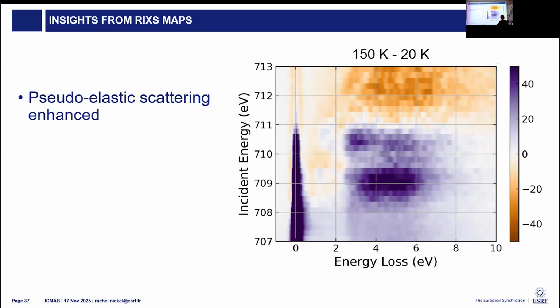I say pseudoelastic because our energy resolution is about 200 meV on this branch, which means that we have both elastic, so 0 energy loss in our elastic line, as well as any other low energy excitation, anything less than 200 meV. So buried in our elastic line, we have phonons, we have magnons, and we could even have a bimagnon. We know that something is changing. It's probably not the elastic. It's most likely related to phonons.